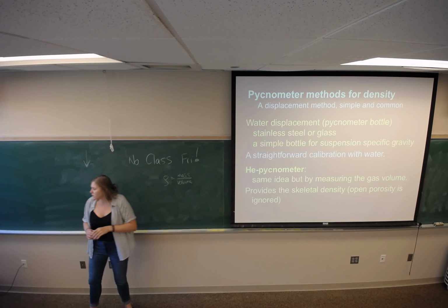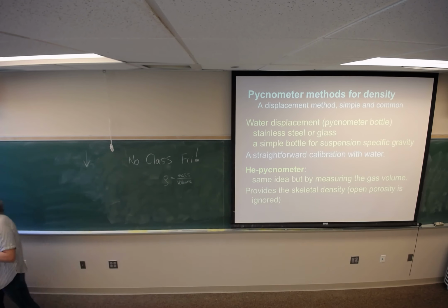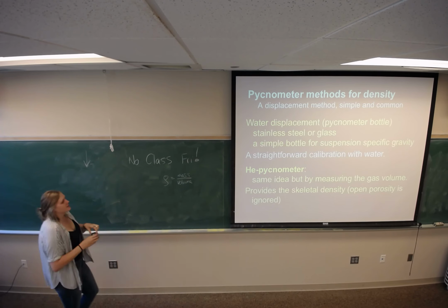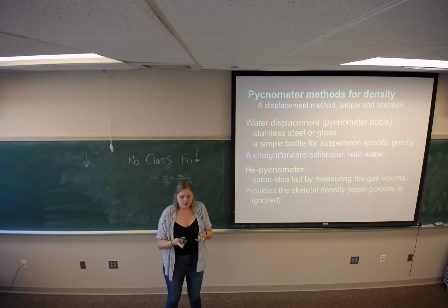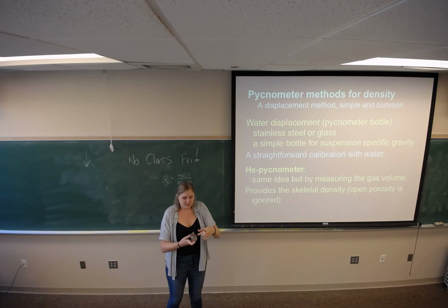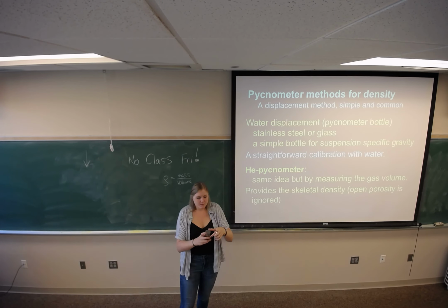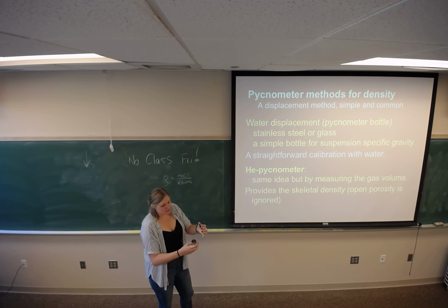One of the common ones we use is called a pycnometer cup, or pycnometer bottle. I just brought this in as an example. Basically this is a container of known volume, and you put your powder or liquid in here, whatever you want to measure, and there's a tiny little hole on the top. Ideally you would fill it up with as much material as possible, and then you close this and wipe off the top to the point where you can't fit any more mass in here.